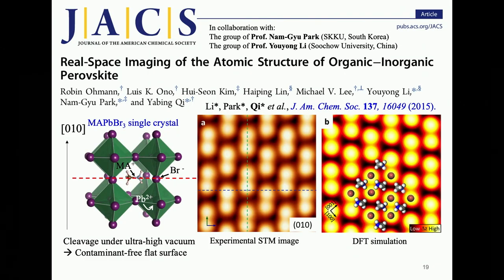By comparing the experimental STM image with the DFT simulation results, we were able to determine that these white protrusions on the STM image, obtained on the reconstructed surface of single crystals, are all bromine ions, which form a characteristic dimer structure. On the other hand, because the MA cation has a much lower surface density of states than the bromine ions, under the typical STM operation condition, they cannot be observed.